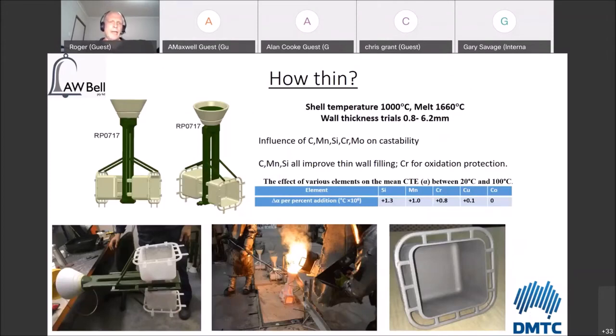Now, it's not a fantastic design for down sprue, but it sort of had some of the characteristics that we wanted to be able to look at. And what you have here is wall thicknesses that vary, the target was between 0.8 and 6.2 millimeters. And we didn't quite get to 0.8 millimeters because when you print at 0.8, it actually came out a little bit thicker just because of the fact that things do move around. But we were able to get down to 1 millimeter where we were targeting the very thinnest walls.